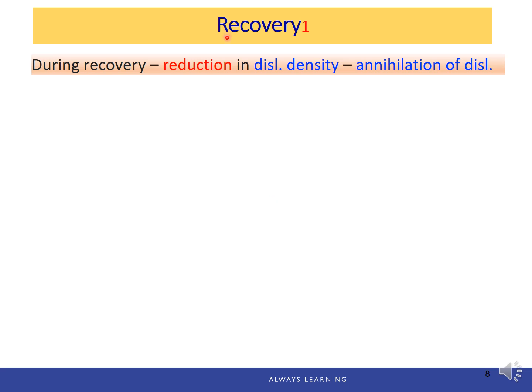The first stage is called recovery. During recovery, some of the stored internal strain energy is relieved by virtue of dislocation motion because of the elevated temperature, so atomic diffusion will be much easier to happen. As a result, there is some reduction in the number of dislocations because of the annihilation of dislocations. So let's see how the annihilation of dislocation happens.